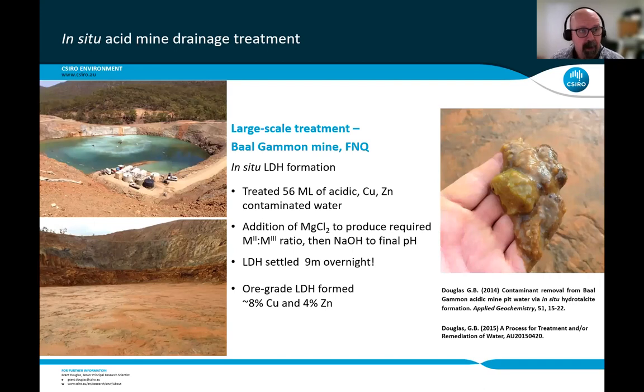So the first one, this is in situ acid mine drainage treatment, and this is from a mine called Baal Gammon, which is located in far north Queensland, if you know Queensland on the Pacific coast. As I said, this involves in situ layered double hydroxide formation. This was treating 56 megalitres, which I think is about 15 million gallons of acidic, copper and zinc and other metal contaminated water. Now in this, to get the actual M2+ to M3+ ratio that we needed, we're aiming for a ratio of 3, remembering we have a 2 to 4 range.